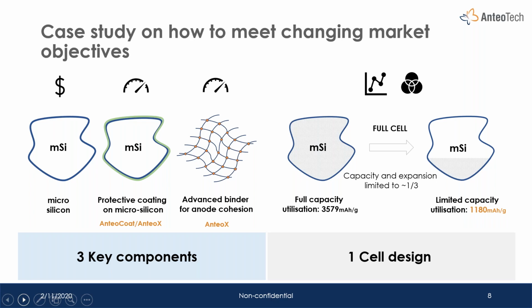Each active material has different properties. And when you talk about microsilicon or silicon oxide or silicon composites, each of them has a different progression of the evolution of this Coulombic efficiency over the initial cycles, which are very critical. This is really where we're focusing on to drive up Coulombic efficiency over the first 5 to 10 cycles to reach in excess of 99% and to get as high as possible. And at this point, it's about maintaining a high level of Coulombic efficiency, so stable cycling performance. And we do address this in different ways using the silicon composite, or a potential new approach being this protective coating on the microsilicon.